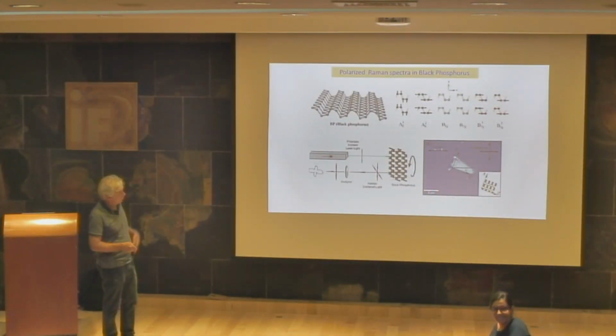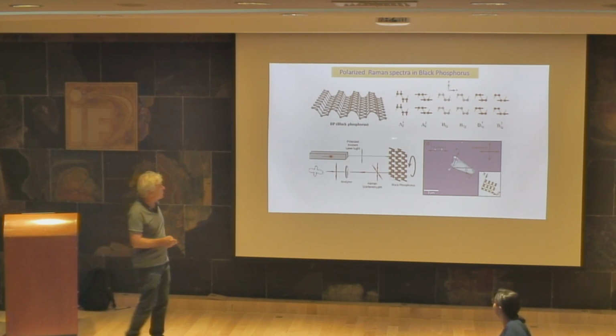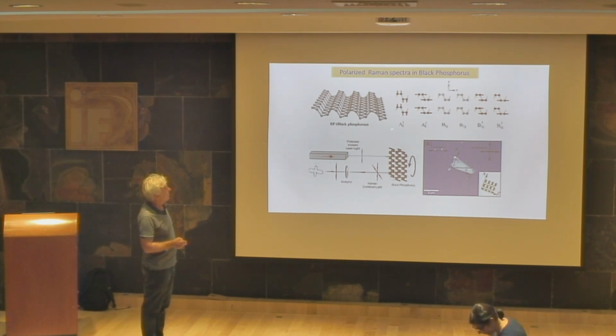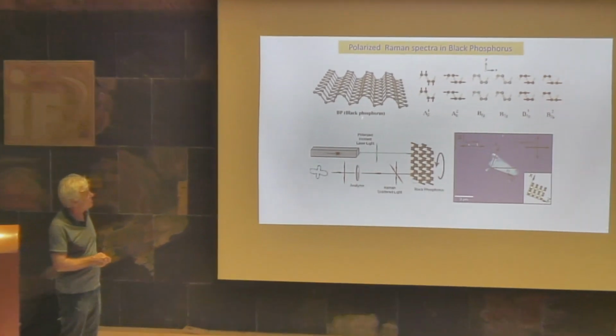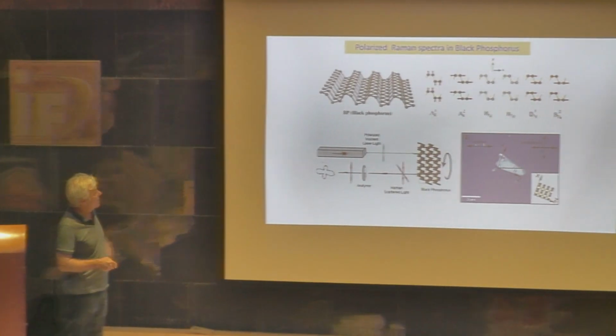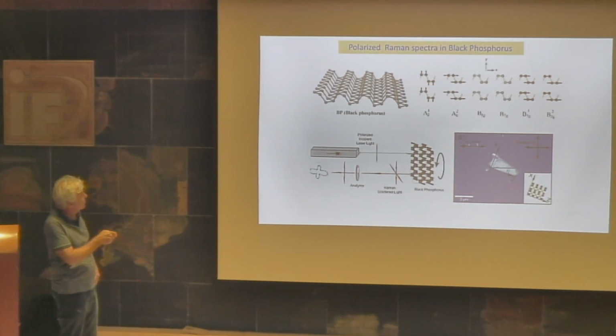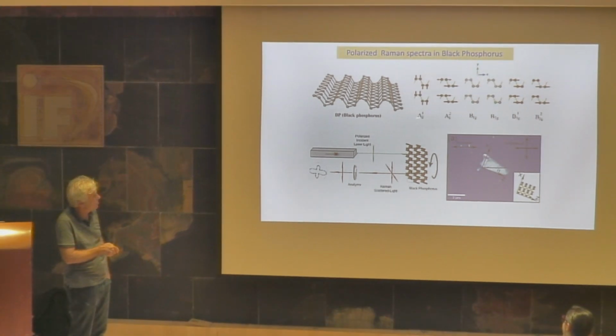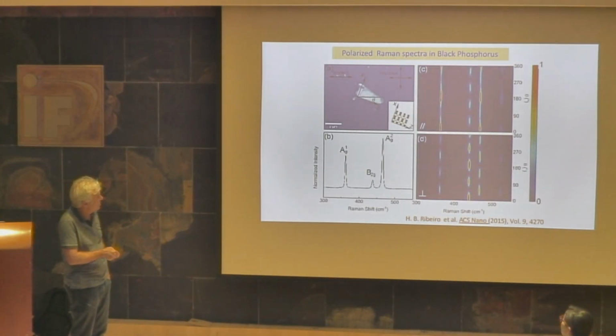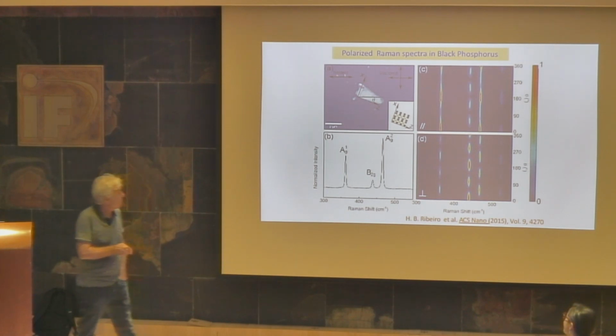Yes. The point is that, for example, in the case of black phosphorus, we have 6 Raman active modes. But when you send the light perpendicular to the layer, we have only 3 modes, which we call AG1, AG2, and B2G. Those are the 3 peaks.